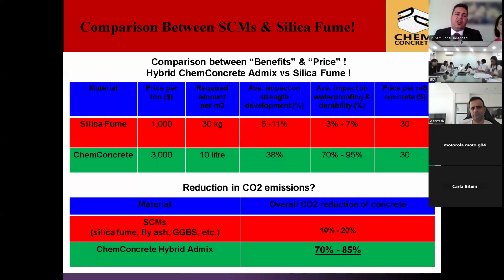So in this slide, one of the traditional methods of improving concrete durability is to use 7 to 15% silica fume. Here we have compared silica fume with our product. You can see, here in Australia, the price per ton for a good quality silica fume is over $1,000 per ton. For our product, this price is specifically for Australia, and it's not applicable to other countries. So the required amount per cubic meter is 30 kilo versus 10 kilo, and then the impact on strength development.